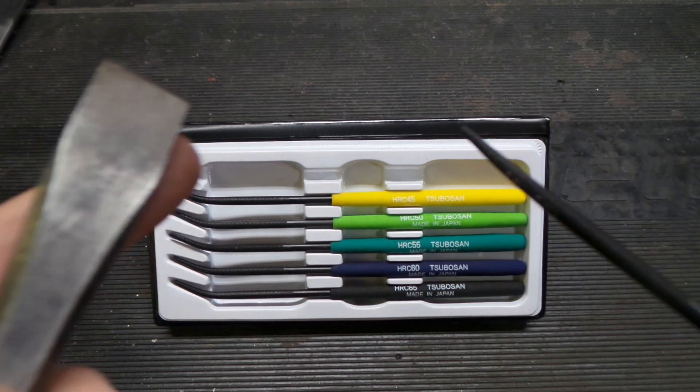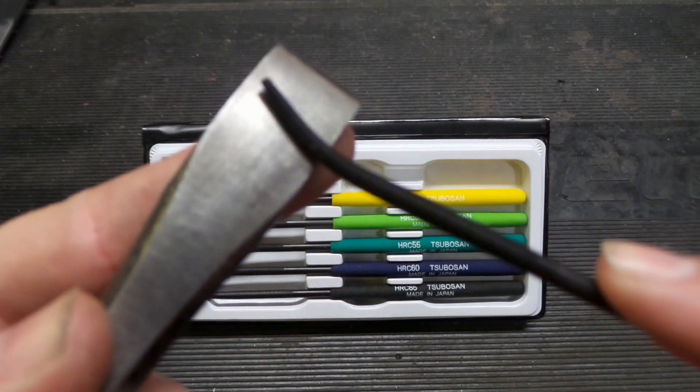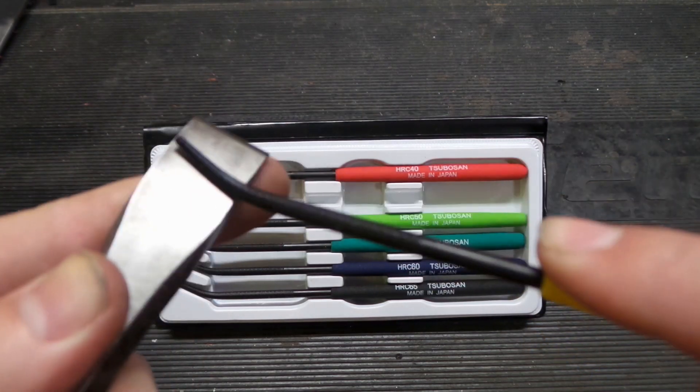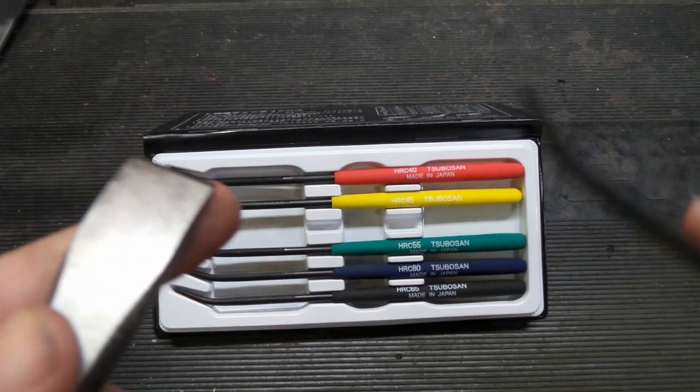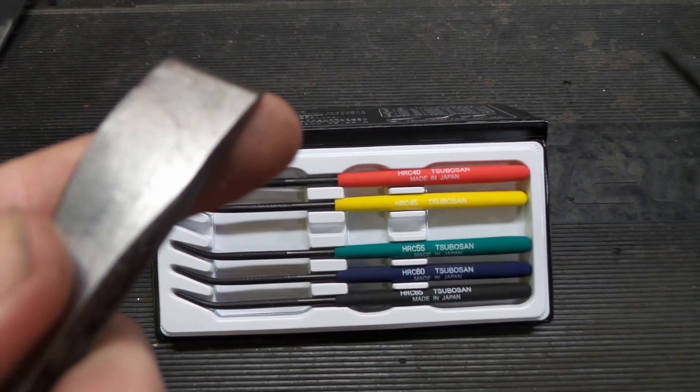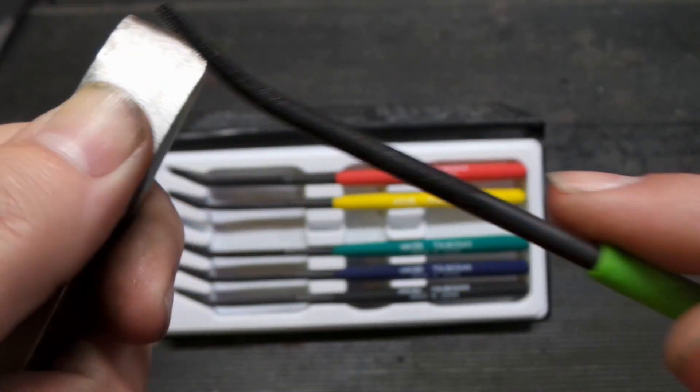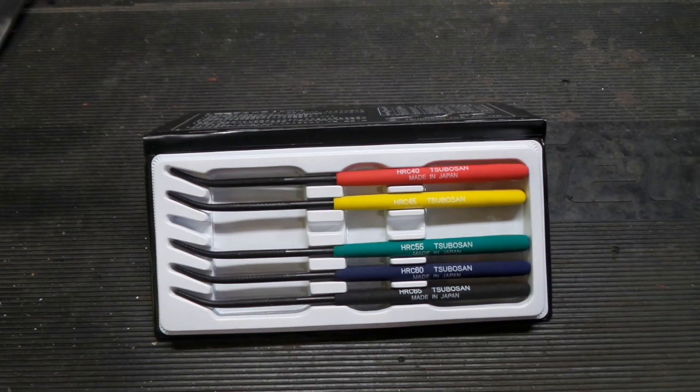And let's see here now at this area. I don't know if you can hear that, it's just kind of gliding over it. So that's definitely harder than 40. We'll just go up the scale. Let's try 45. It's got a little bit more grab but it's still not really grabbing in. I think you could hear it was sliding. So 50 seems to be starting to get a bite. And that sounds about right. Yeah, we're getting a bite in that on 50. So this is about 50.